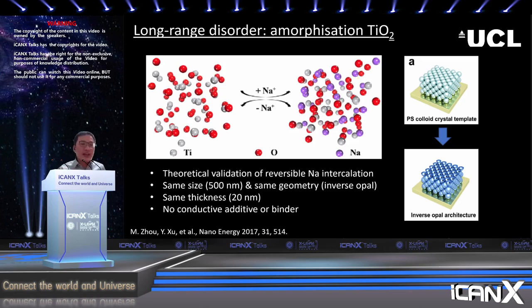So that got me thinking, can we use non-crystallized titanium dioxide, which is the amorphous titanium dioxide, to achieve the same or even better performance? Can we use the defects that are caused by the amorphization of the material to contribute to the capacity? I think the answer is yes. We started from the simulation work to verify that sodium intercalation is actually reversible in the amorphous structure of titanium dioxide. And we deliberately chose atomic layer deposition as our synthesis technology.